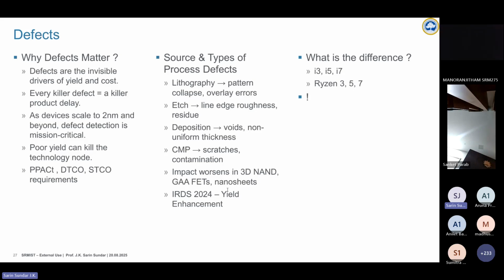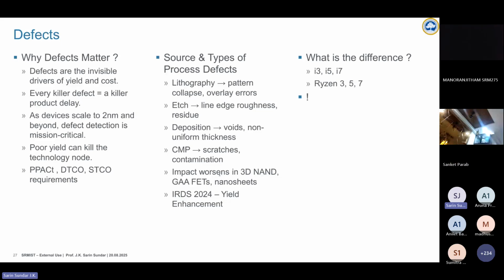And here is a very short list of defects, and some of the major ones. The sources of defects in lithography are pattern collapse, overlay errors, line edge roughness, and residues during etching. In deposition, it is thickness non-uniformity or voids, and in CMP you have scratches, and the impact entirely worsens when you go for 3D architectures. And there is a separate document on IRDS. IRDS is the old ITRS, the roadmap, and the 2024 edition has a yield enhancement chapter. Probably I'll also show you one picture from that.